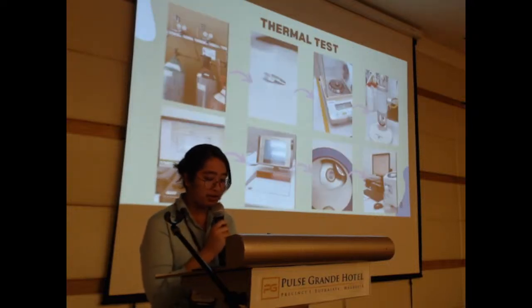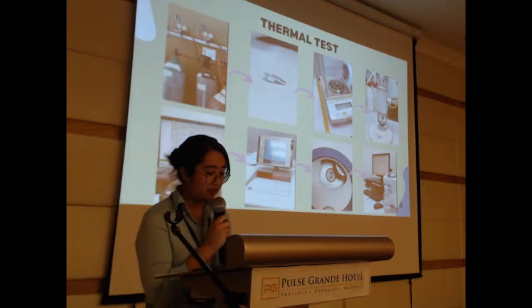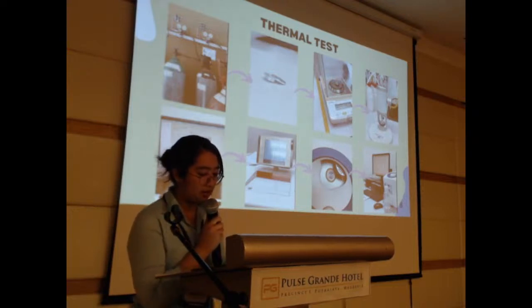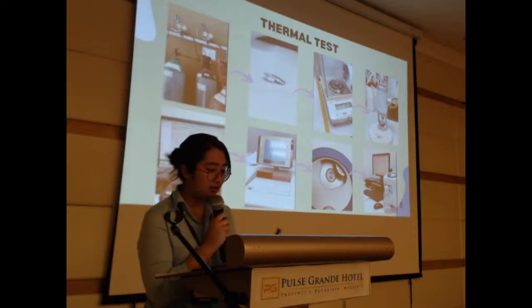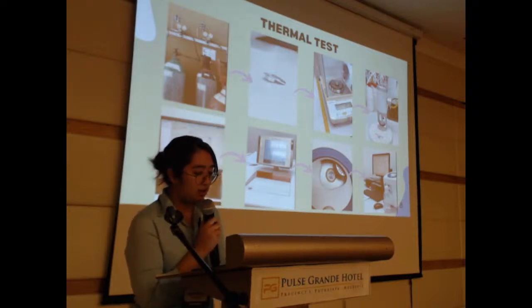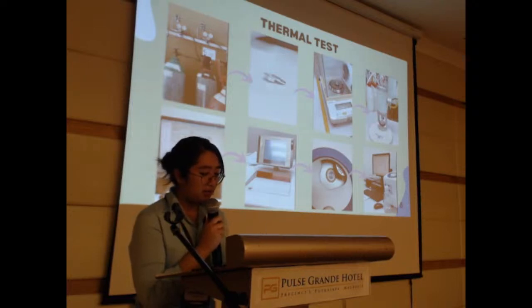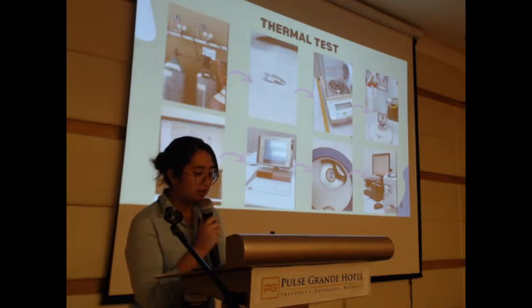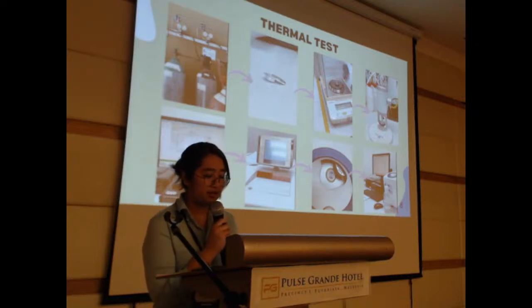So the first experiment is to run the DSC machine with the leftover debris from the solder alloys. We can use about 5 milligrams for each of the solder alloys in the DSC machine. Nitrogen gas will be used as the medium because it is more stable. The sample will be placed in a sealed crucible and placed in the DSC machine. And the temperature ranges from about 100 degrees Celsius to 300 degrees Celsius, then back from 300 degrees Celsius to 100 degrees Celsius, so that we can have the phase diagram. We wanted the exothermic and endothermic peaks of each of the solder alloys.